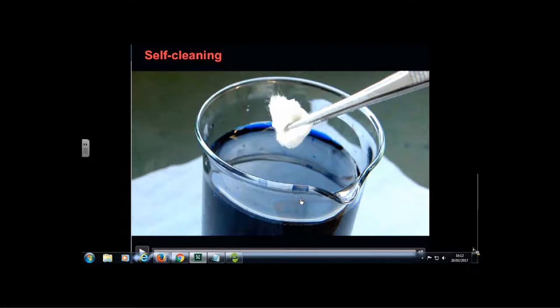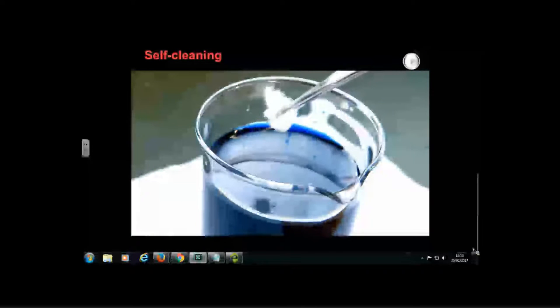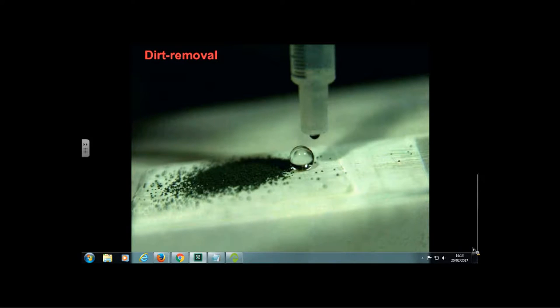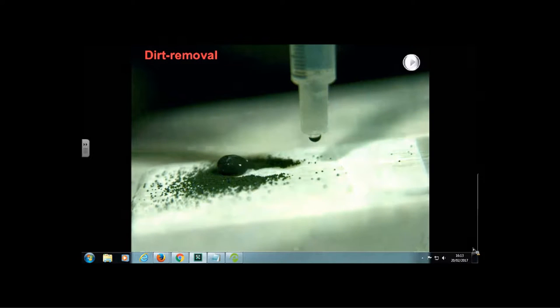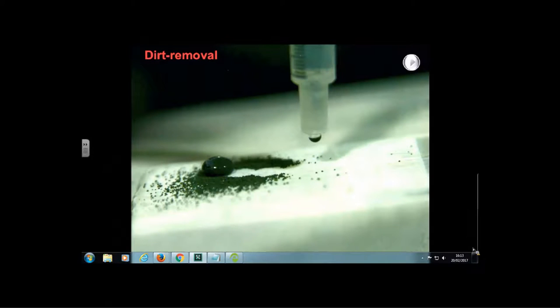Materials can also be made very resistant to dirt and dye. A solution of methylene blue — a very strong staining agent — is used to dip the superhydrophobic cotton wool we've made. When put into the dye solution and taken out, it is absolutely pristine with no wetting at all. This also shows the rolling motion of water droplets on a dust-covered surface: the droplet picks up the dust as it moves, acting like a miniature vacuum cleaner, picking up dirt, dust, and in nature, bacteria.